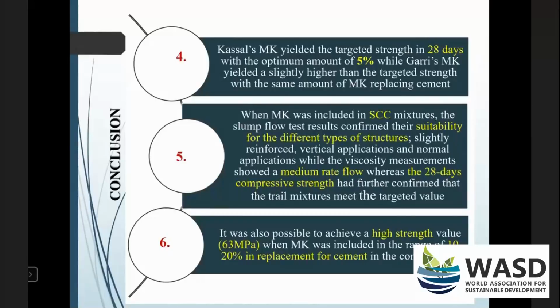It was also possible to achieve high strength values for the concrete that included metakaolin, and we got up to 63 megapascal when metakaolin was included in the range of 10 to 20 percent replacement for cement.